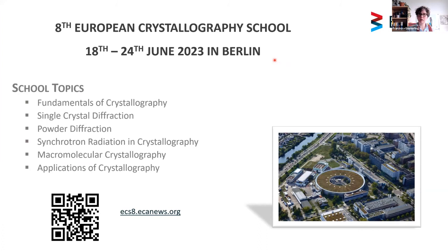But if you think about the diffraction pattern I showed for the in situ data, also at the end, the crystallite size is, let's say, in a typical co-crystallization experiment between 100 and 200 nanometers, which is not that bad also for structure determination. And usually we do it also with our in-house instruments. So these are not synchrotron data. It's a specialized instrument in that it's a capillary instrument, but you can still perform normal measurements and solve the structure.